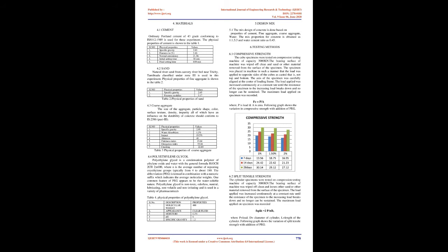5. Design mix. 5.1 The mix design of concrete is done based on properties of cement, fine aggregate, coarse aggregate, and water. The mix proportion for concrete is obtained as 1:1.5:3 and the water cement ratio as 0.45. 6. Testing methods. 6.1 Compressive strength.